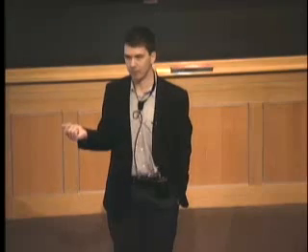So that's one thing. You'll find that the hard part is often figuring out exactly what calculation to do and how to put the numbers together to get a physical quantity. And then you'll also learn something about the things we talked about here, what kind of results potentials give. For example, I'll already tell you, you'll find that the vacancy formation energy is very close to the cohesive energy, something we discussed, we talked about.